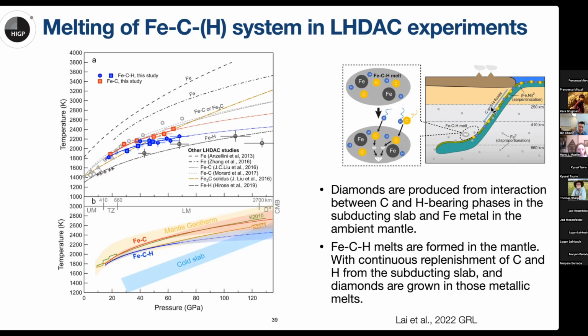So this would indicate that if carbon and hydrogen sources were carried by the subducting slabs, and reacted with iron in the mantle to form the iron-carbon-hydrogen alloy, then when it is closer to the mantle geothermal condition, this iron-carbon-hydrogen would be molten. This would create an ideal environment for the formation of macro diamond under those high P-T conditions. And if you have hydrogen in the system, that would further facilitate the formation of the diamond from the iron-carbon-hydrogen liquid.